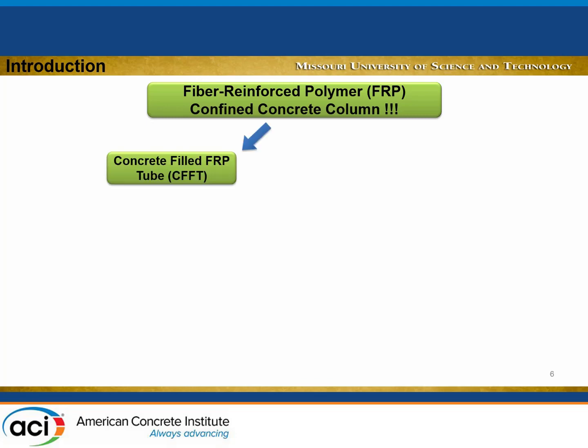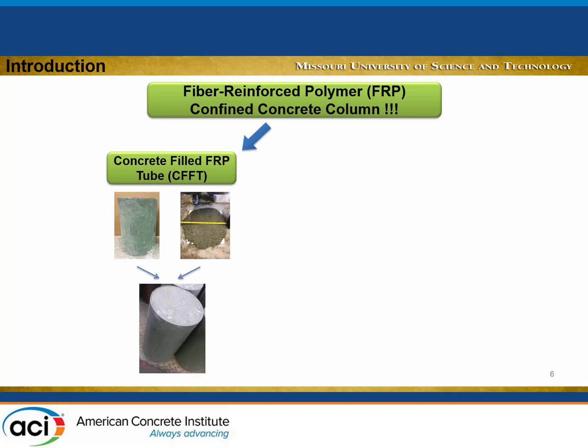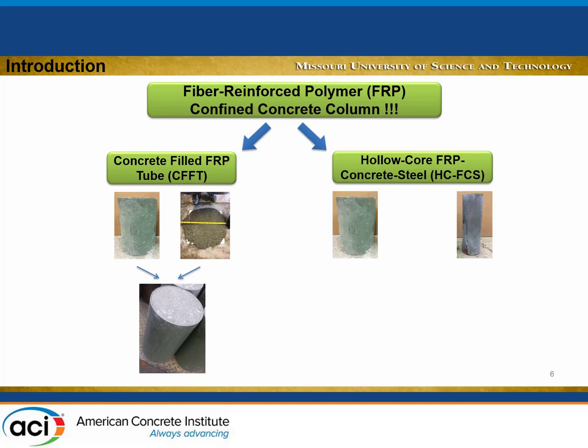The other option is to look for alternative construction systems that may be more durable. So we're looking at two different systems. One of them is concrete filled fiber tubes, and over here we use just SCC, self-consolidating concrete, to fill the tubes. Here is a tube after filling. The other system is relatively quite new, hollow core fiber concrete steel columns. The system is a composite section. You have an outer glass fiber and inner steel tube, and fill in between the two tubes with, again, self-consolidating concrete. We have already done some larger scale testing, like half scale testing under cyclic load for this system.